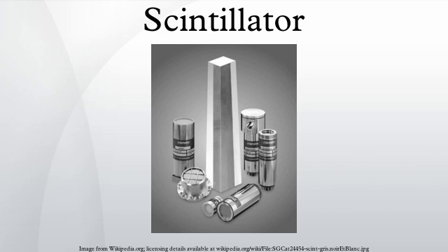The holes associated with electrons in the conduction band are independent from the latter. Those holes and electrons are captured successively by impurity centers, exciting certain metastable states not accessible to the excitons. The delayed de-excitation of those metastable impurity states again results in scintillation light. BGO is a pure inorganic scintillator without any activator impurity.